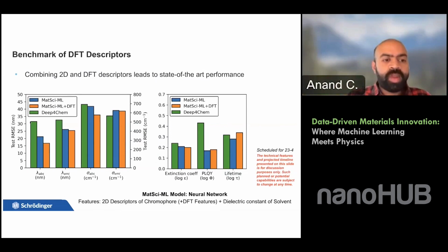So the Deep4Chem is the one that was published in literature. The blue line is MatSci-ML, which is our internal benchmark, a Schrodinger machine learning model. And the orange bar is the Schrodinger machine learning model with DFT descriptors. And for most cases, we see that adding DFT descriptors is an improvement, producing a reduction in the root mean square error for most of the properties.